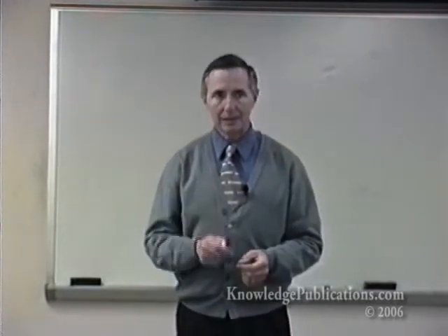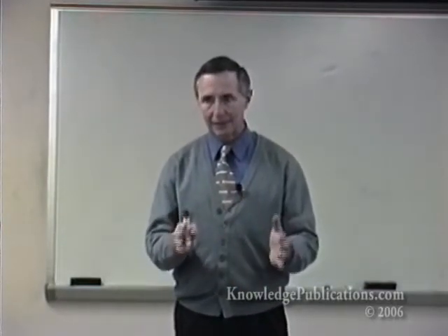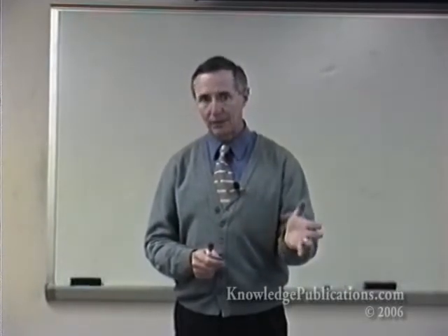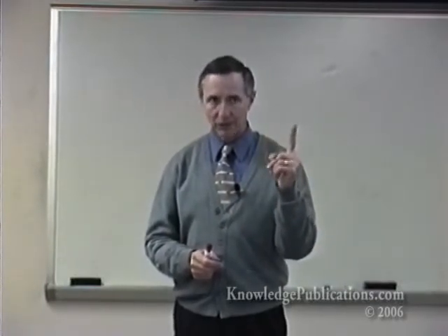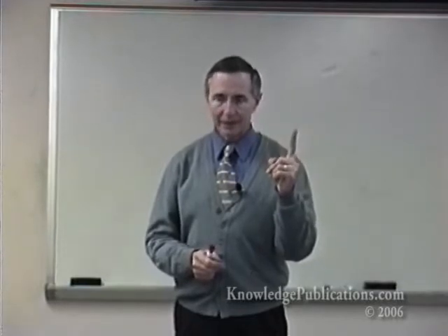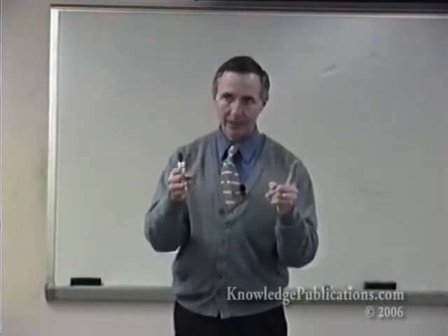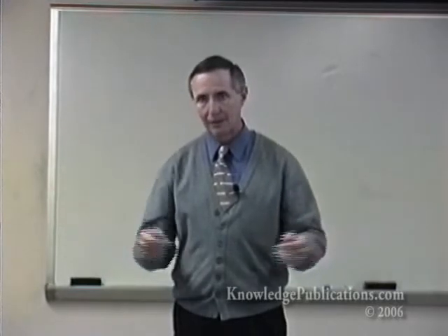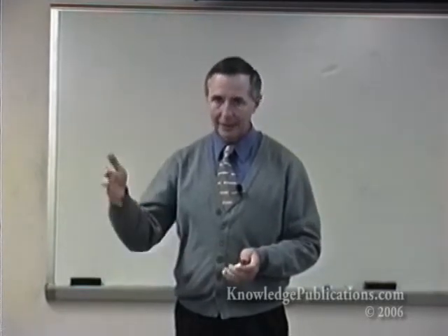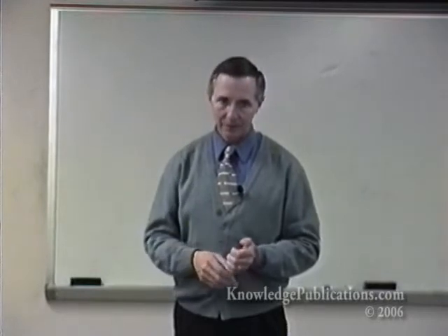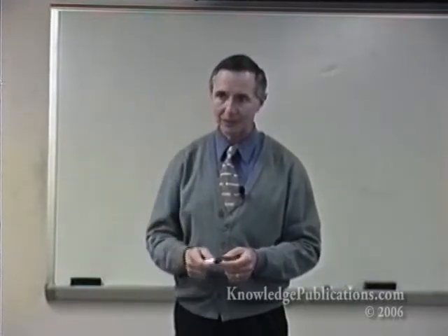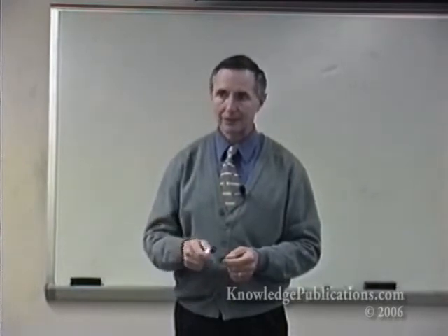Brittle failure in these types of galvanic cells is going to happen anywhere that there's one more ingredient we haven't mentioned, and that's moisture. All you have to have is that dissimilar combination and moisture, and you'll get the failure. It's a matter of time. There's another type that is from the outside in failure that is due to household cleansers that find those flex couplings, particularly the chlorides.